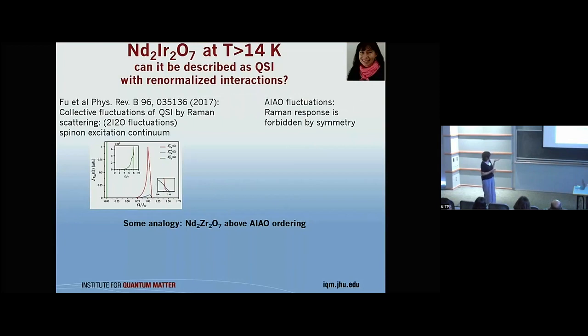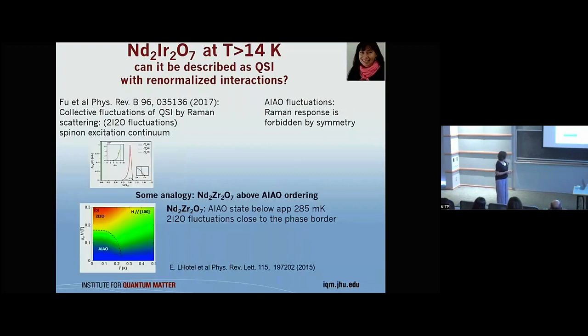And again, Natasha's group had a paper long ago predicting a strong response of quantum spin-ice, and neodymium zirconate is actually one of the systems where we should look for it. But because everything is happening at very low temperatures, which are very technically challenging for Raman scattering, we haven't got there. So indeed, neodymium zirconate is some kind of analogy, because it does order all-in, all-out at a quarter of a Kelvin, but it does have two-in, two-out fluctuations above, when it's out of the state.